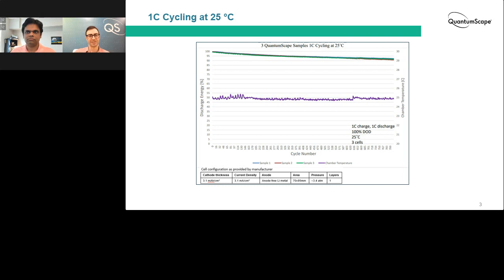1C charge, 1C discharge. So 1C, for those of you who don't know, means the battery is charging at a rate that would completely charge the battery in about 1 hour. So it's charging in an hour, discharging in an hour. Each cycle was done to full depth of discharge, that is between 0 and 100% of the state of charge at room temperature, like I said. And what this shows are 3 cells that are progressing together with very modest energy fade to 800 cycles.